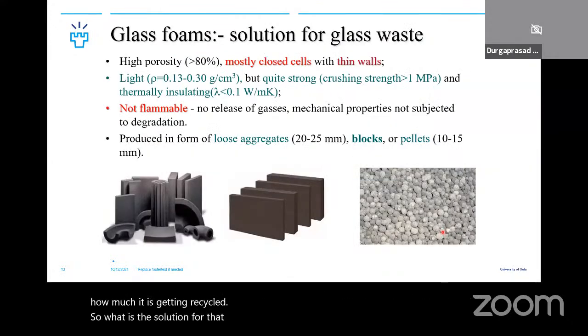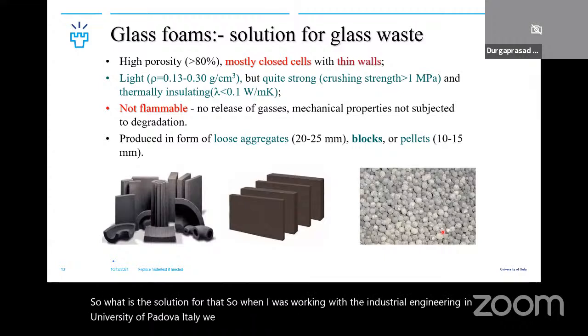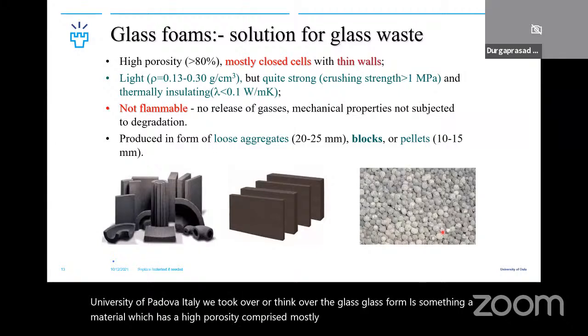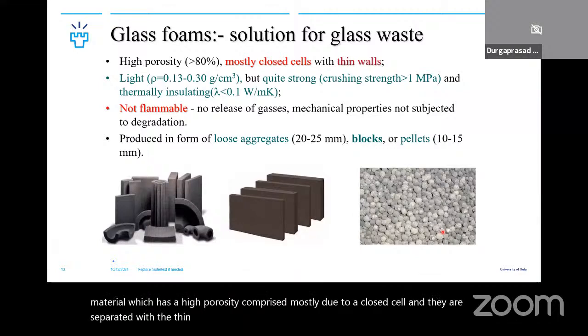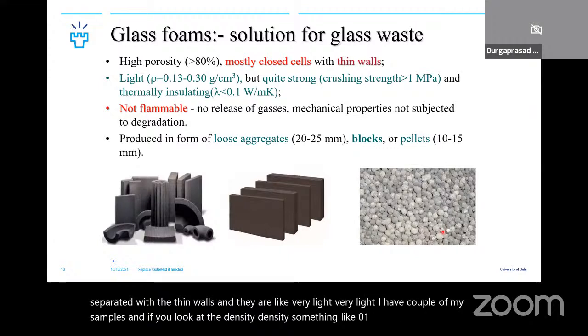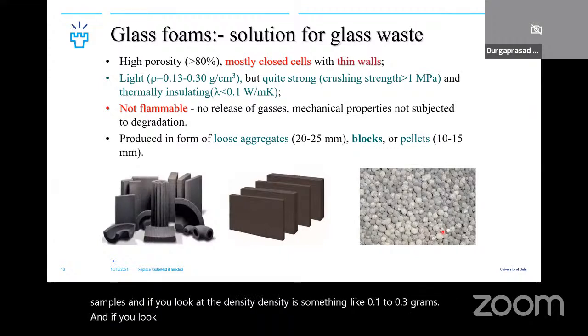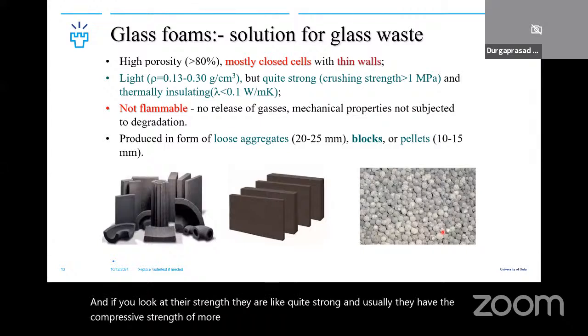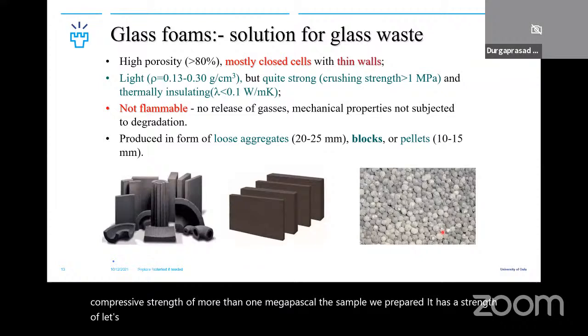When I was working in industrial engineering at the University of Padua, Italy, we thought about glass foam. Glass foam is a material which has a high porosity, comprised mostly of closed cells separated by thin walls. They are very light. I have a couple of my samples. The density is something like 0.1 to 0.3 grams per cubic centimeter. And they are quite strong. Usually they have a compressive strength of more than 1 megapascal. The sample we prepared has a strength of around 8 megapascal.